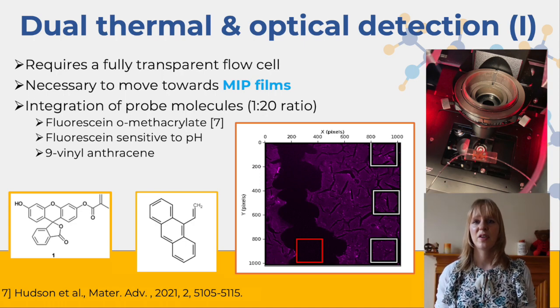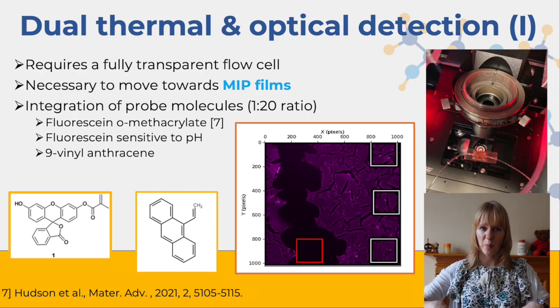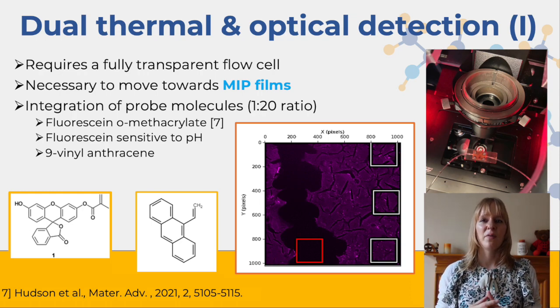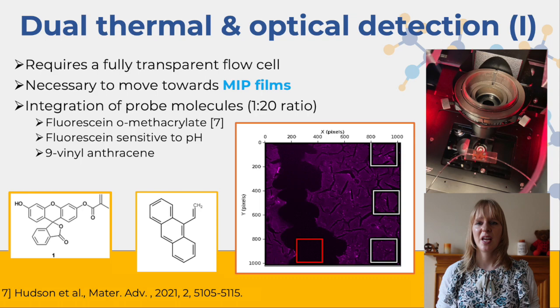Then the second change that we made is, rather than using these microparticles, which were definitely unstable if we looked at prolonged periods of time, we started looking at films. So this is a very thin layer that was deposited onto glass chips.